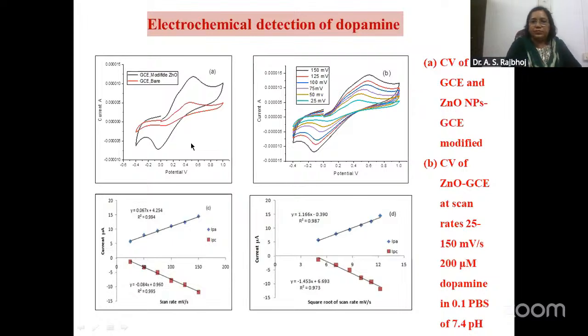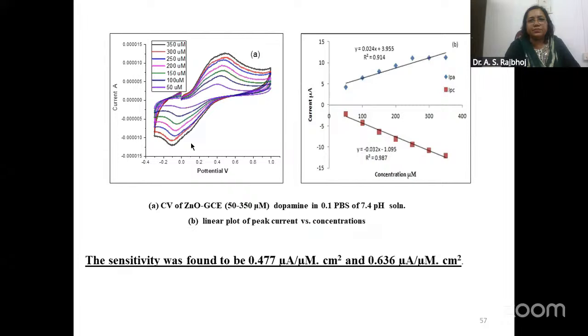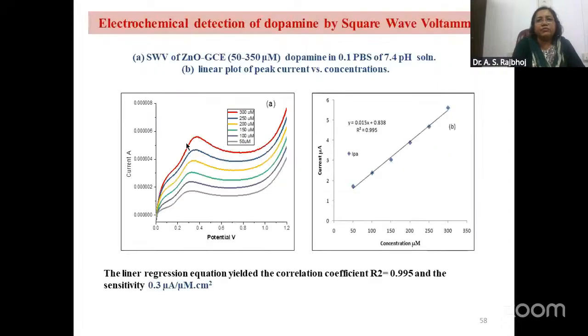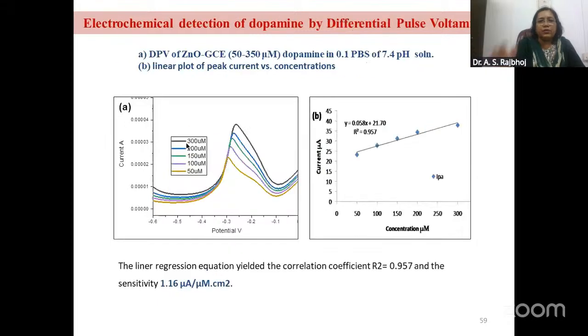Here you can see again the different scan rates in the electrochemical study, that is, cyclic voltammetric studies. The sensitivity has been found to be 0.477 microamperes per micromolar per centimeter square and 0.636 microamperes per micromolar per centimeter square. So this is what was found for zinc oxide nanomaterials. Now similarly, we have done the square wave voltammetry, and this is the differential pulse voltammetric study.